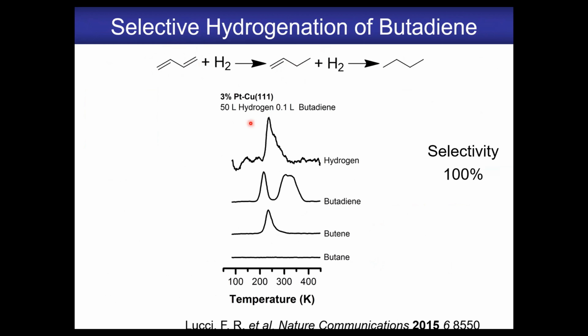And what we see on a 3% single atom alloy platinum copper surface is 100% selectivity to butene, no butane, and no high temperature hydrogen. So we're not decomposing the molecule. So that looks very promising.